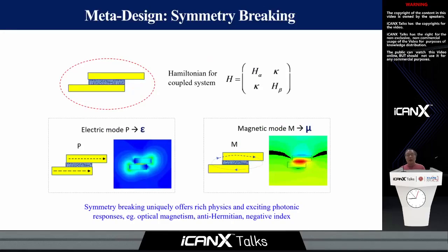So to illustrate how this idea works, I will use a very simple example with two nanorods with symmetry breaking along the longitudinal direction. These two coupled nanorods with an offset in the longitudinal direction can give us very exciting physics and photonic responses, as shown here. It will not only give the electric response from the coupling, but it can also give a magnetic response from this two nanorod coupling, and can also generate both electric and magnetic modes. It can also generate many exciting properties such as optical magnetism, anti-Hermitian coupling, as well as index controllability.